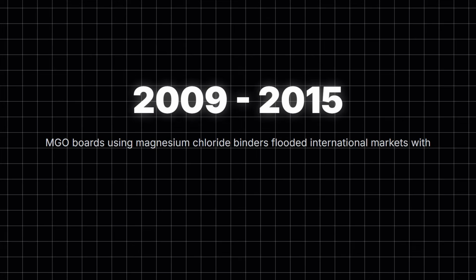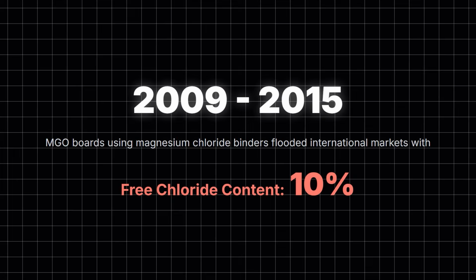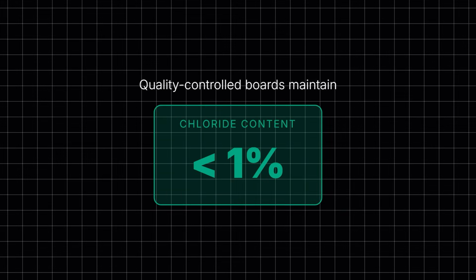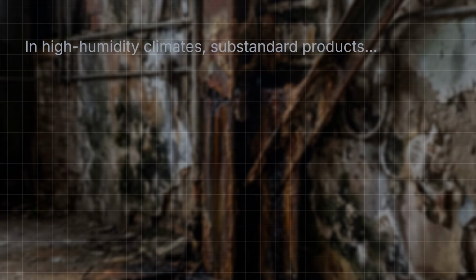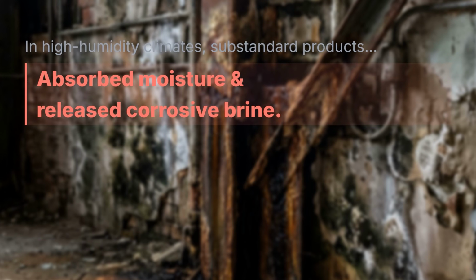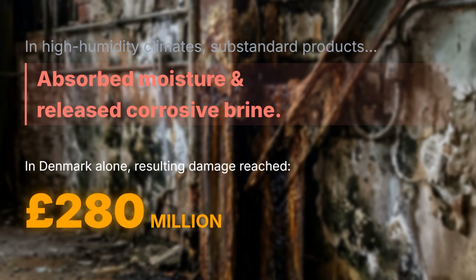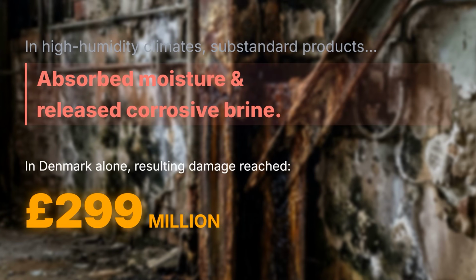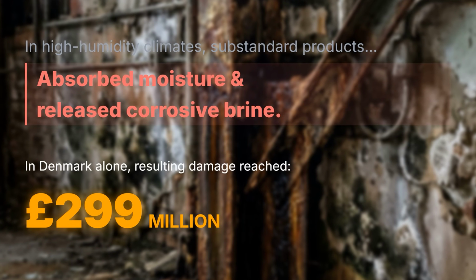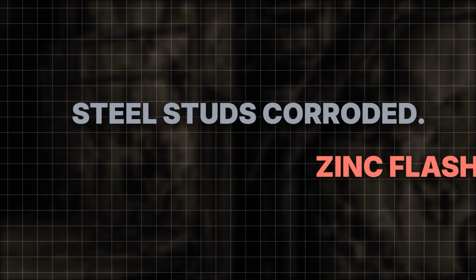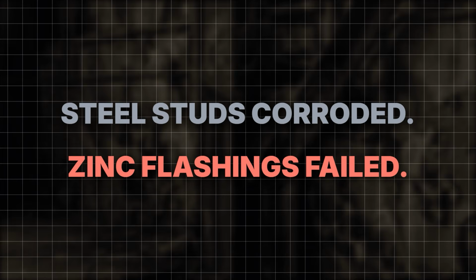Between 2009 and 2015, MgO boards using magnesium chloride binders with free chloride content of 5 to 10% flooded international markets. Quality-controlled boards maintain chloride content below 1%. In high-humidity climates, the substandard products absorbed moisture and released corrosive brine. In Denmark alone, resulting damage reached approximately 300 million British pounds. Steel studs corroded. Zinc flashings failed.